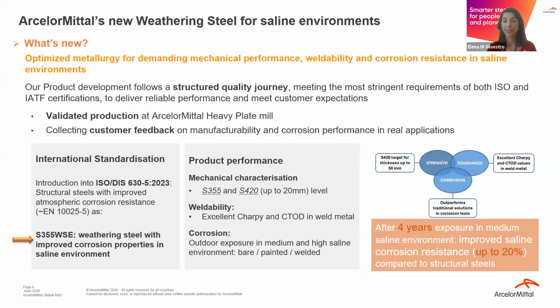And then we also tested extensively our material in corrosion. So we had, first of all, accelerated corrosion tests, but then we moved to outdoor exposure in medium and high saline environment and in different conditions. So we have just the material as it is, let's say bare steel. We also exposed painted steel, and we exposed as well welded steel, with the outcomes that Krista will show in the next slides. Maybe just as a summary of the corrosion performance that we got after 4 years of exposure in medium saline environment, we saw an improvement in saline corrosion resistance up to 20% compared to structural steel, which is quite a good result.